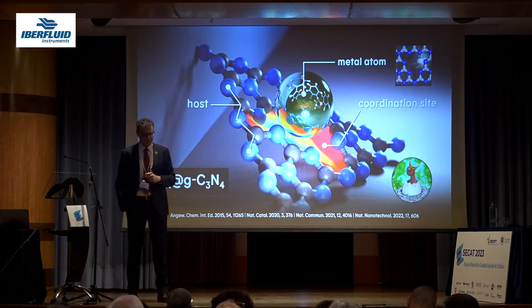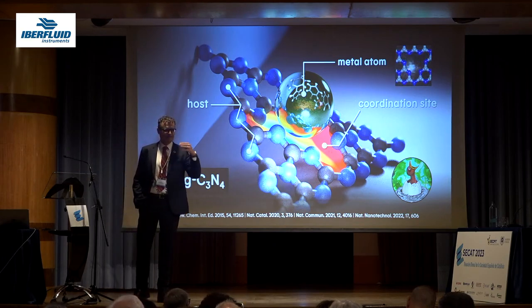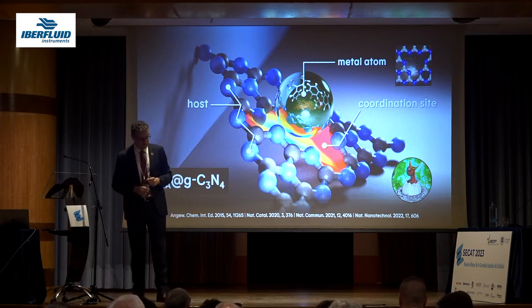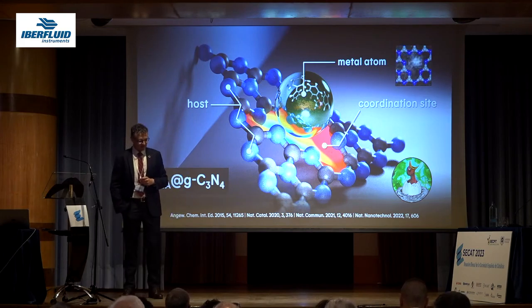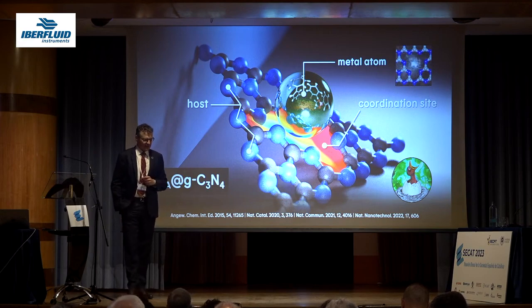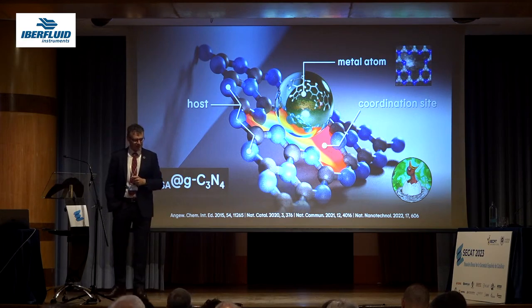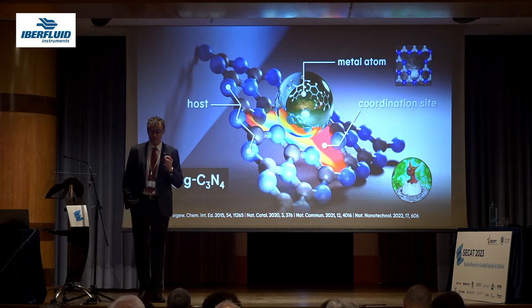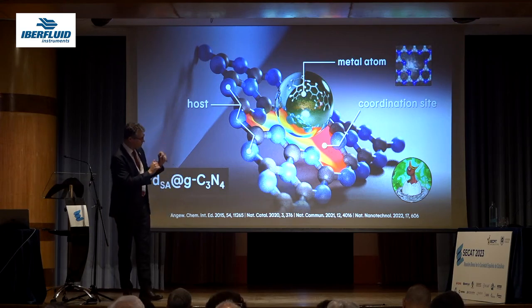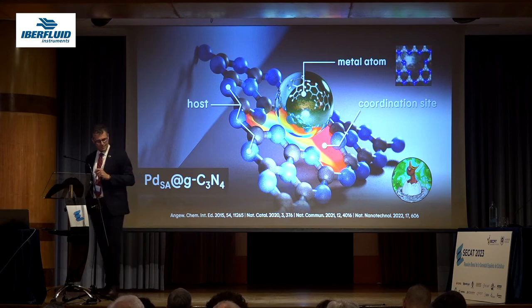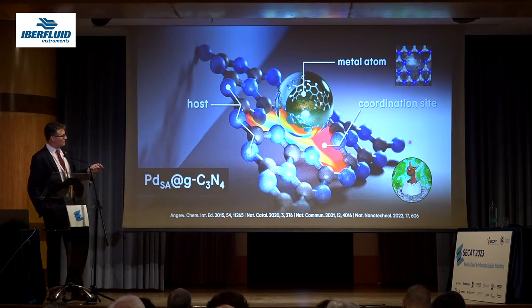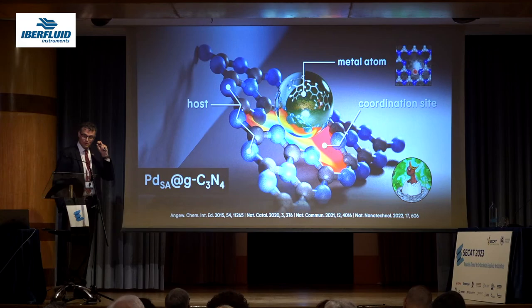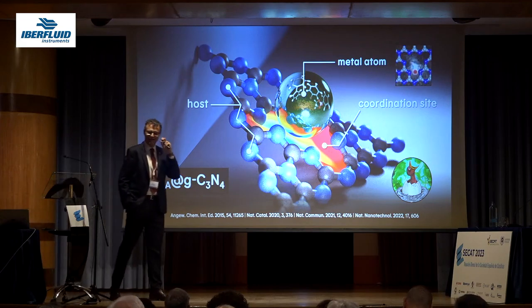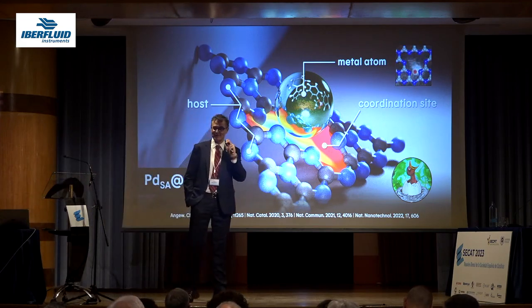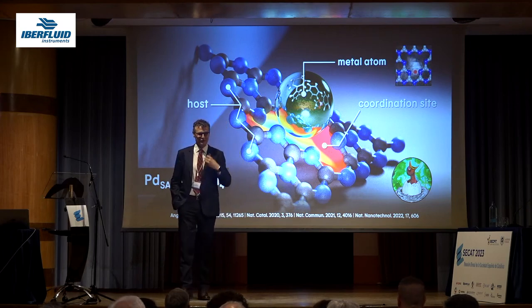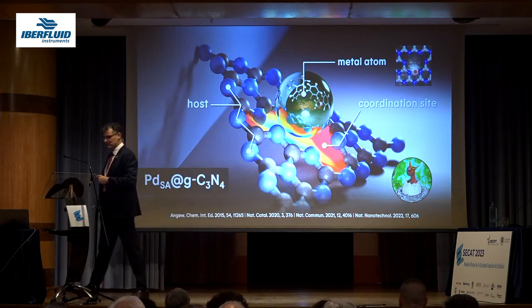And what can we use these single atoms for in another dimension or in another area of research? And this is the first catalyst that we developed in 2015. It's palladium single atom stabilized on graphitic carbon nitride, on these beautiful cavities of carbon nitride. And you can see here, very stable. So the single atom upon, let's say, operando imaging stays on the cavity, right? Despite the electron density of the microscope, so very stable.